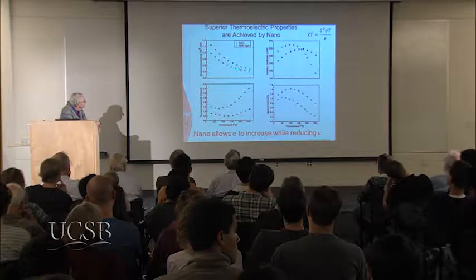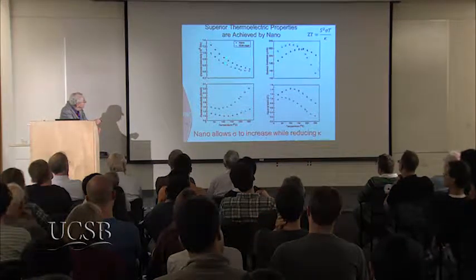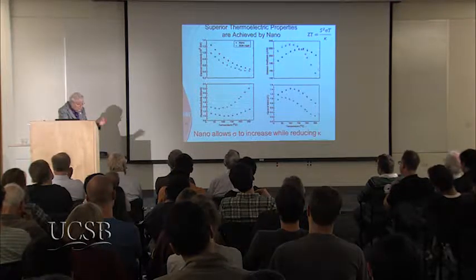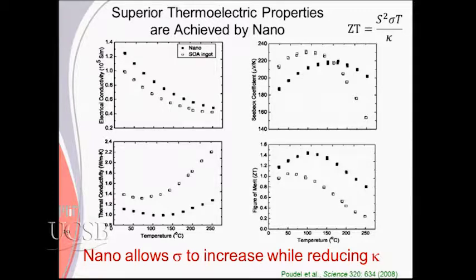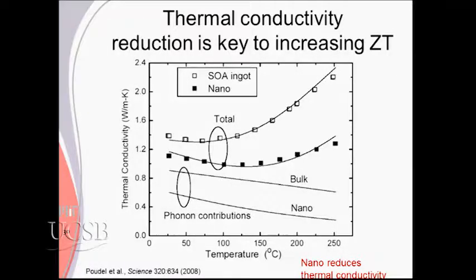So electrical conductivity, we could make nano with doping. You see nano improves for the same sample, just nano it and it improves. And thermal conductivity really gets much lower. So if you put the whole thing together, you get something that's very promising, 40%. So that was the very first effort that we had where, on the same samples, we did all of these things, to show proof of principle works when you actually make larger quantities. So scale up was proved, and lots of other people have done much better than this, but this was, to my knowledge, probably an early work in the field. And the thing that was the most important was knocking down the thermal conductivity.